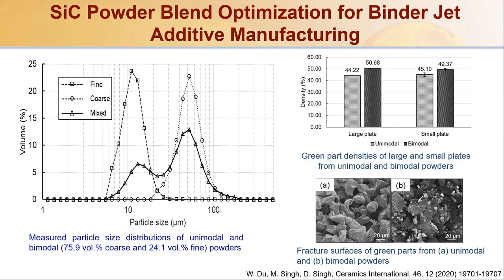So, for example, if you look on the left side, there is a particle size distribution of unimodal and bimodal powders. Basically, this is the composition which came out of the modeling, roughly around 76-24. And when we use these powders to print silicon carbide plates, we do see about 4-5% improvement in the green densities. The reason is that in those big gaps, the small powders are basically filling up.